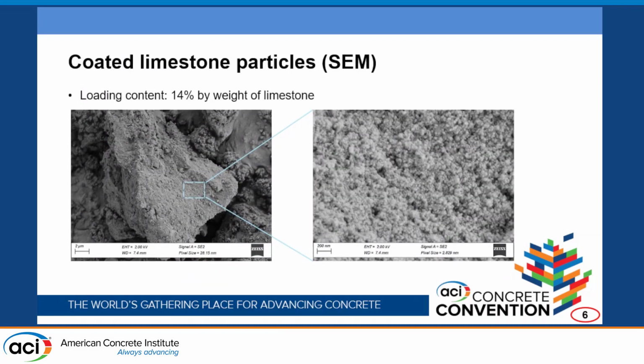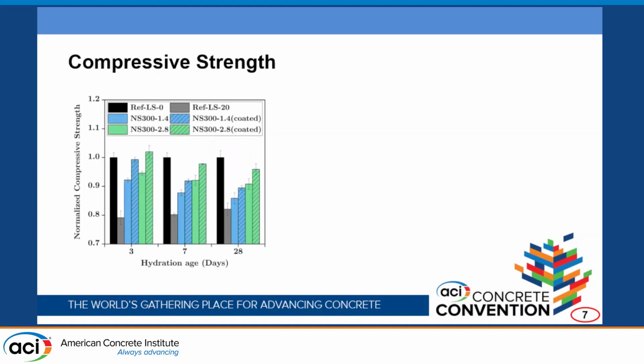The next thing you can see here is an SEM image of the coated nanoparticles on the calcite surface. You can see that it is a multi-layer deposit of the nanoparticles, nanosilica, on the surface of the calcite. Now we can see the results of the compressive strengths up to 28 days of curing. So we actually cured the samples. I forgot to mention that.